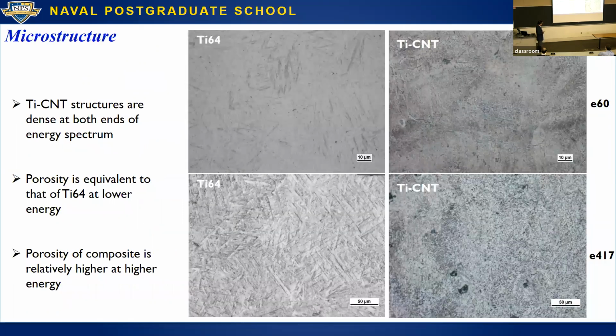So these are kind of the microstructures that we obtained. These are just optical micrographs for now. Just wanted to give you a general idea. We get pretty good density in the products. And one of the biggest differences that you can notice as a function of energy, you actually get more porosity at the higher energy density. And there's different sources of porosity. I'll talk about it in the next slide.